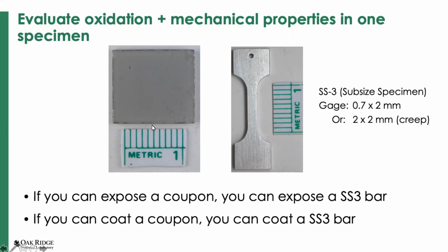I recently got a quote, and I was paying a little over $20 each to have coupons machined from some cast materials that I needed to evaluate. And typically these tensile specimens, depending on the machine shop and how busy they are, we're paying $50 to $75 a piece. So relatively modest increase in the cost of the specimen. And honestly, if you can test a coupon, you can test a tensile specimen. And if you can coat a coupon, you can probably coat a tensile specimen. Again, if you really want to know what those properties are.